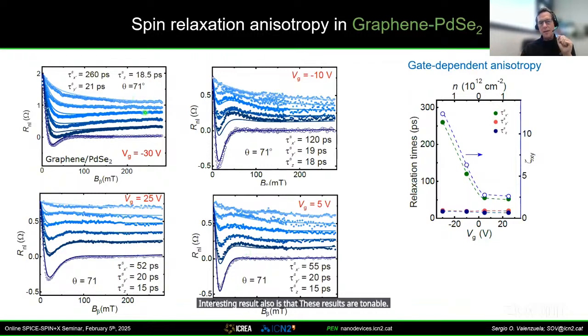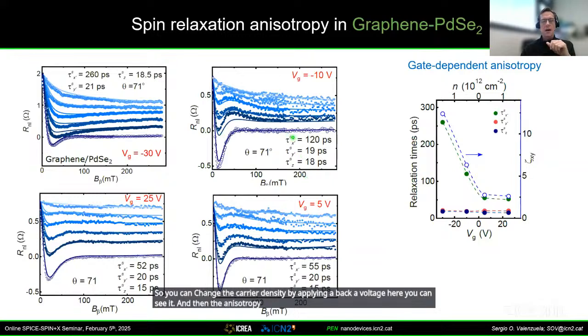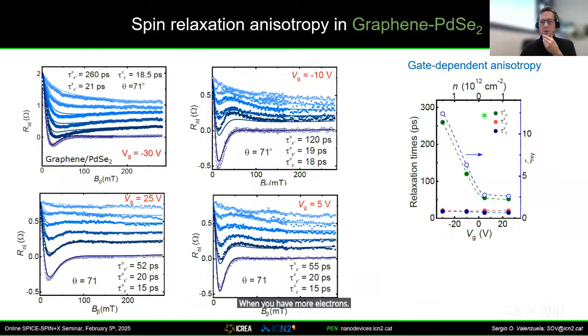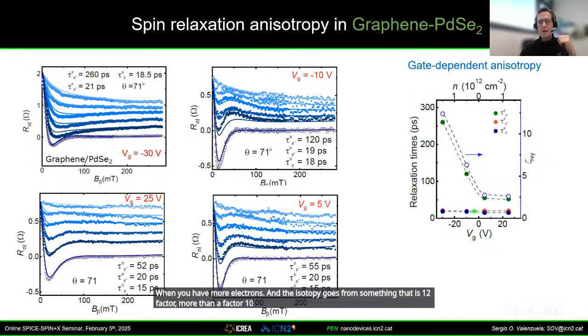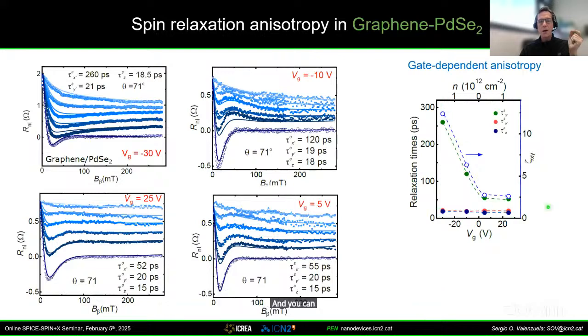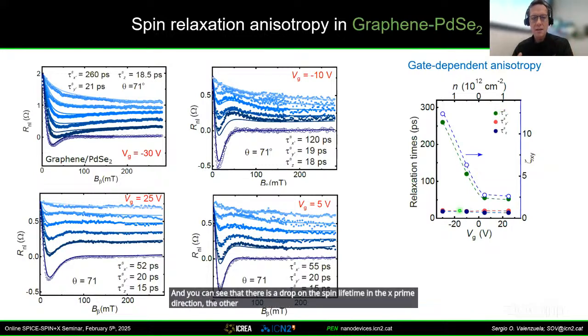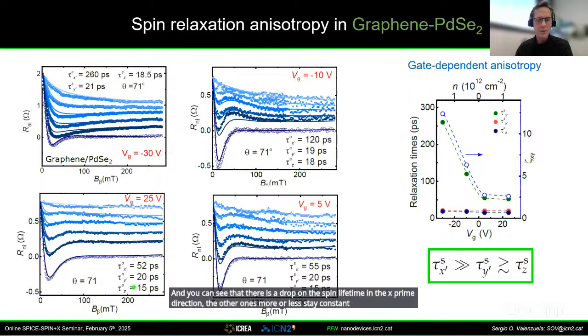You can change the carrier density by applying a backgate voltage. Here you can see it. And then the anisotropy actually changes. The anisotropy in this case goes smaller and smaller if you go towards the right here with positive voltage, when you have more electrons. The anisotropy goes from a factor of more than 10, about 12, to 2.5, but it's still significant. And you can see that there is a drop in the spin lifetime in the X prime direction. The other ones more or less stay constant. And you can see that here in these values.